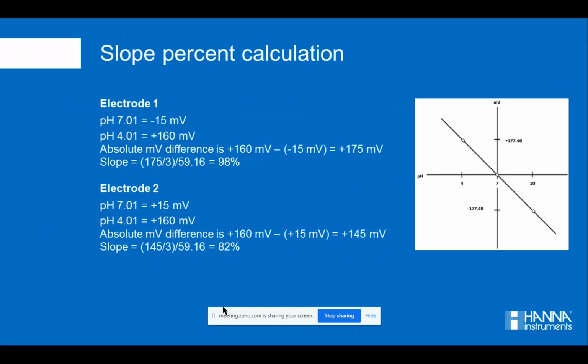If you could see on your screen the slope percentage calculation, there are two examples of two electrodes, electrode 1 and electrode 2. Electrode 1 is calibrated at 7 and 4, and similarly electrode 2. But electrode 1 is giving out a good slope of 98%, whereas electrode 2 is giving out a very bad slope of 82%, which is not within the acceptance criteria. Then why has the slope dropped in electrode 2?